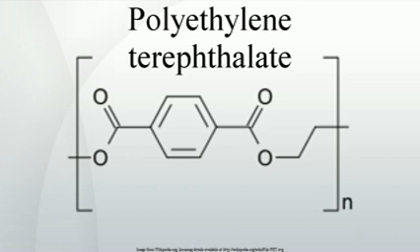Similar to total glycolysis, methanolysis converts the polyester to dimethyl terephthalate, which can be filtered and vacuum distilled. Methanolysis is only rarely carried out in industry today because polyester production based on dimethyl terephthalate has shrunk tremendously, and many dimethyl terephthalate producers have disappeared. Also as above, polyethylene terephthalate can be hydrolyzed to terephthalic acid and ethylene glycol under high temperature and pressure. The resultant crude terephthalic acid can be purified by recrystallization to yield materials suitable for repolymerization. This method does not appear to have been commercialized yet.